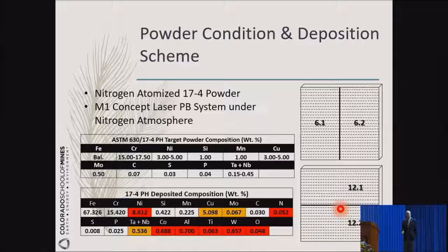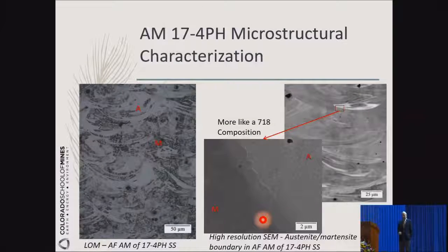The other one here is to look at the base target composition of 17-4 and the deposited composition. Right away you see those red boxes showing you the different composition that you get. You see the nickel composition particularly is different, going from the original nominal composition of 3 to 5 to about 8.6%. And I'll point out the nitrogen composition, very much higher than the expected composition, and oxygen, 0.048%, also too high compared to its composition.